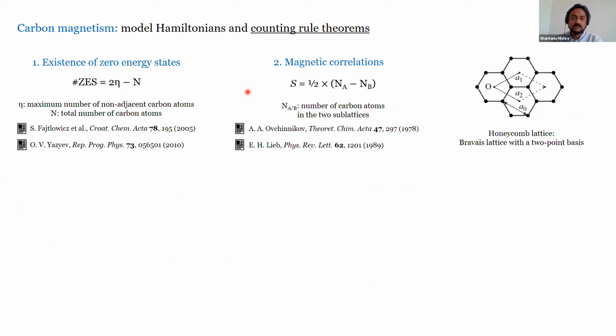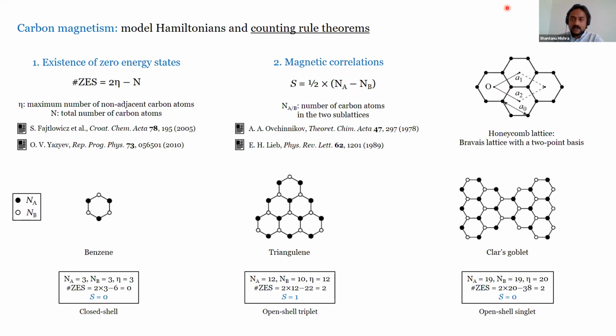And the second is, given that you have zero energy states, what could be the possible magnetic correlations between the electrons? This is given by Lieb's theorem, which says that the total ground state spin quantum number of your system should be half times the difference in the number of carbon atoms belonging to the 2 sublattices. And the definition of sublattice, of course, comes from the fact that the honeycomb lattice is not a Bravais lattice, but it can be considered to be a Bravais lattice provided you take a 2-point basis, and then these 2 inequivalent carbon atoms are the 2 sublattices. And now you can apply this to the following 3 nanographenes of interest.